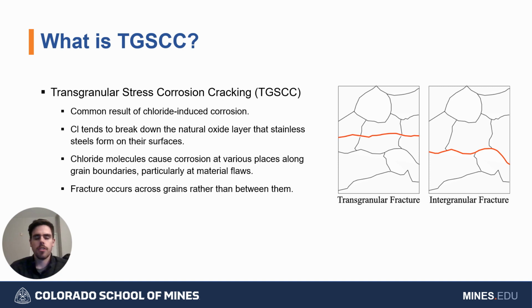For considering the fracture of stainless steel climbing anchors, there is one particular mode of material cracking that's responsible for this, and that is transgranular stress corrosion cracking. This is a type of stress corrosion cracking that is uniquely chloride induced. So the chlorine tends to break down natural oxide layers that form over metals. Particularly in the case of stainless steel, it's so potent that it overcomes the chromium and molybdenum oxide layers.